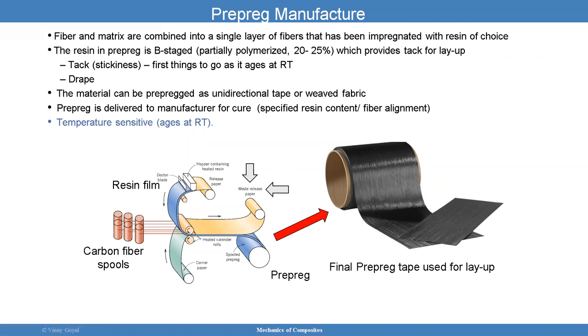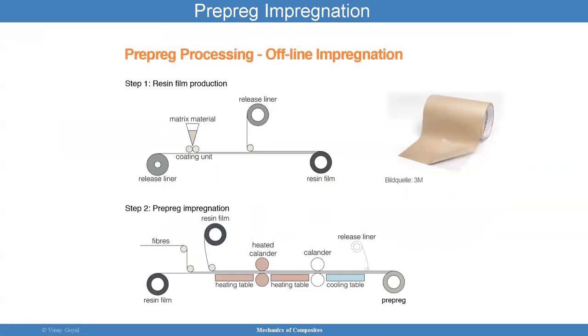And I'll stack it up to get the highest performance I want for my application. And the idea there is to then cure it to get a solid laminate. You have prepreg processing, which is offline impregnation. You have the resin film production, which is done separately. And you have a release liner, typically a release film.